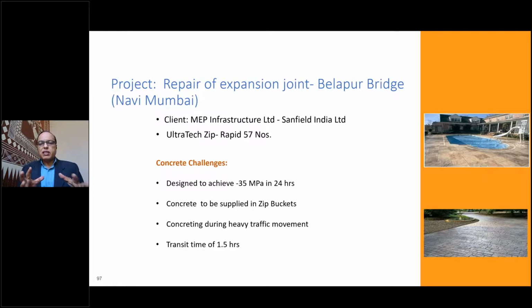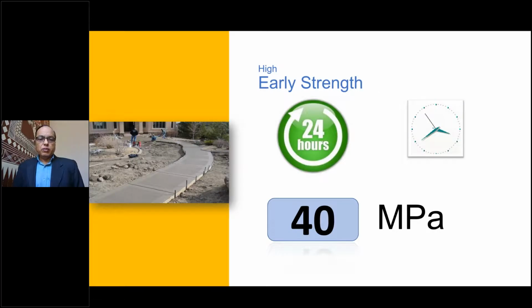Therefore, concrete was supplied in small quantities, zip or the bucket concrete, we call it. It was supplied in such small quantities, and the transit time was about 1.5 hours from the RMC to the site. And concreting has to be done during a very heavy traffic movement, and within 24 hours it should be ready for use. The next case is furthermore high early strength concrete. Can we get 40 MPa in 24 hours? That is the challenge. That is a possible thing.